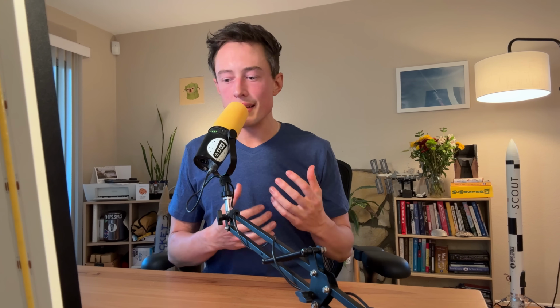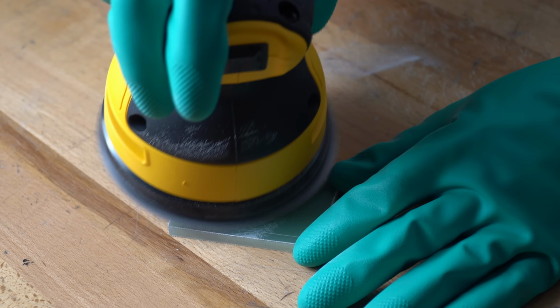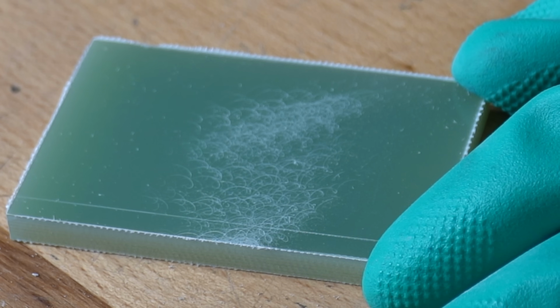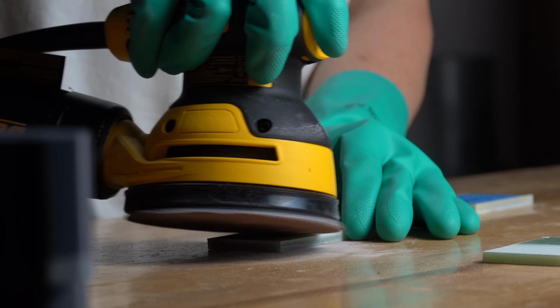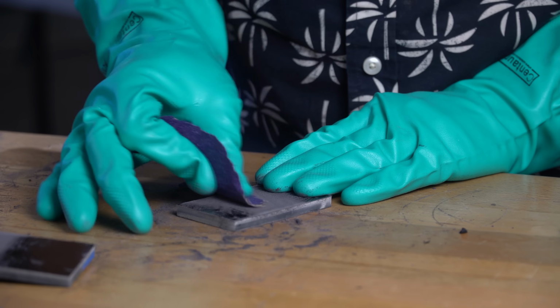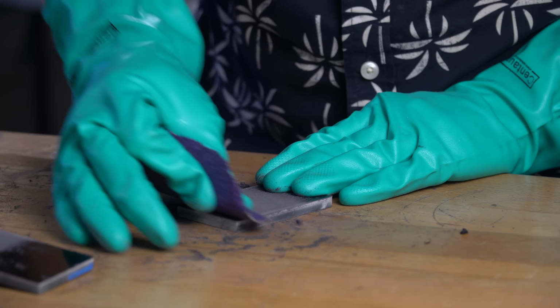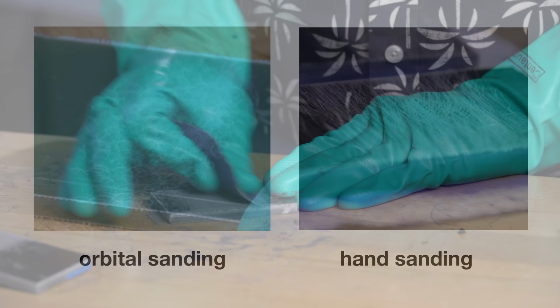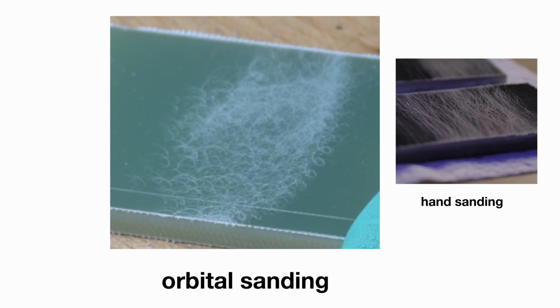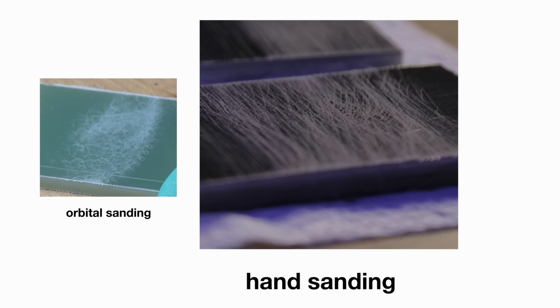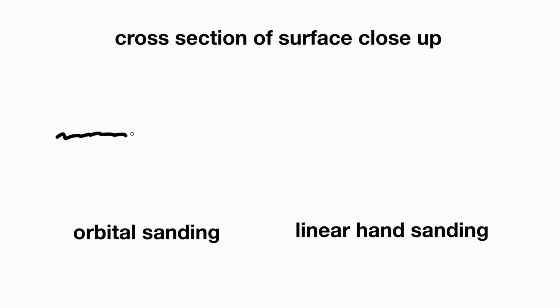I started to think a little harder about how the orbital sander works, and it's in the name. It sands in an orbit with tiny little swirls. The sander vibrates while rotating the sandpaper, and that creates lots of little swirls on the surface. For hand sanding, I had largely moved my hand back and forth in straight lines. The difference here is that with a large enough area and a distributed load, the orbital sander probably leaves a flatter surface overall, whereas hand sanding cuts deeper grooves. It's as if the orbital sander is creating tons of micro scratches in a uniform surface, whereas linear sanding cuts deeper and likely results in more surface area for the epoxy to bond with.